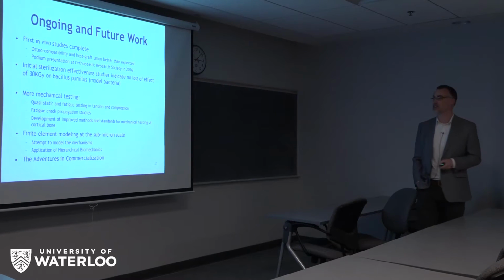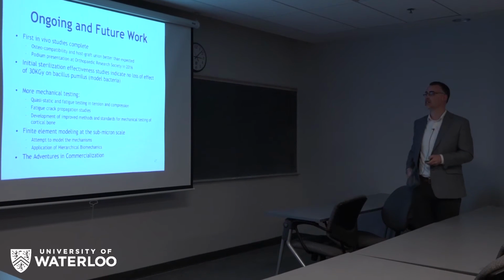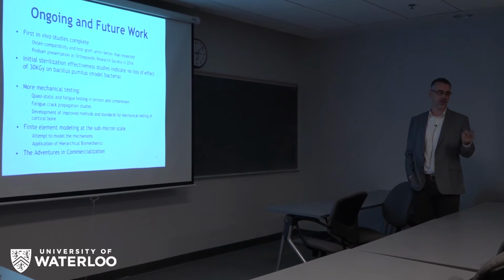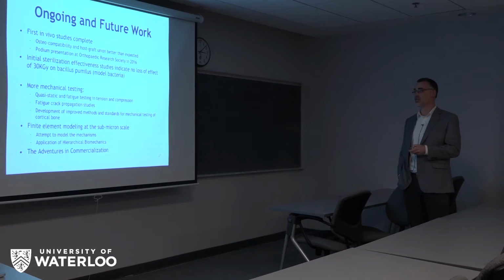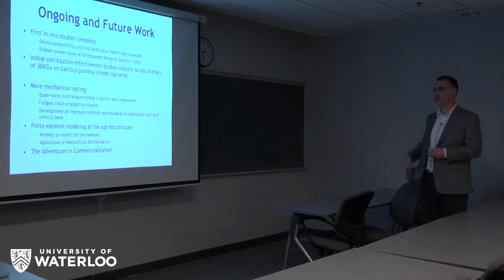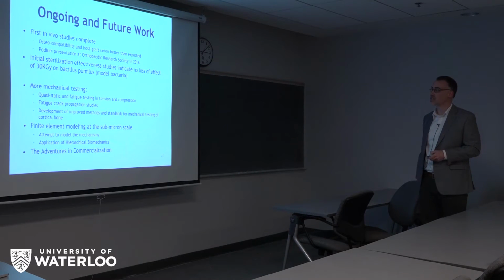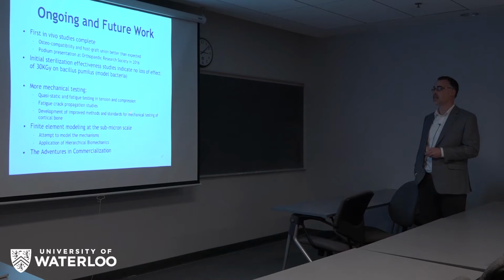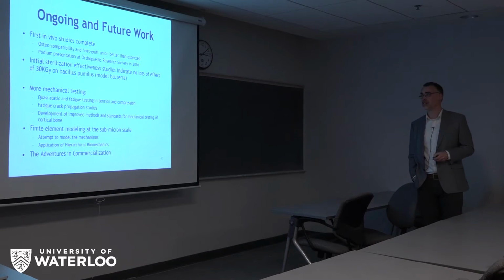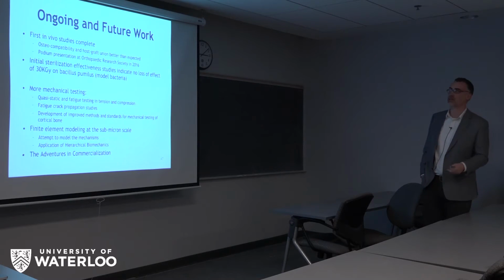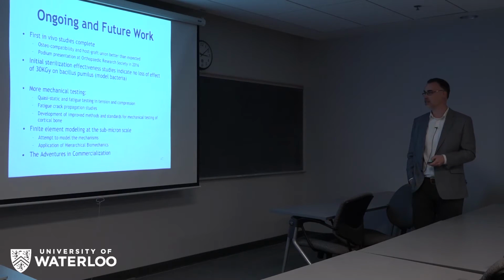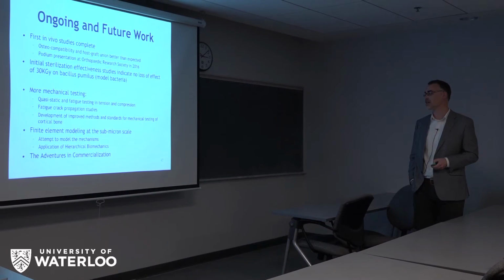So right now, I have a master's student back in Toronto who is finishing up our first study in vivo, where we used a rabbit model to do a segmental defect and reconstruct it with normal, irradiated, and ribose and irradiated bone. It's going really well. Better than expected results, and he's been invited for a podium presentation in March at the Orthopedic Research Society. We're very excited about that. And we did some work with bacteria to see what effect the ribose pretreatment has on effectiveness, and it seems to have no effect. It seems to have killed all the bacteria, which is great.